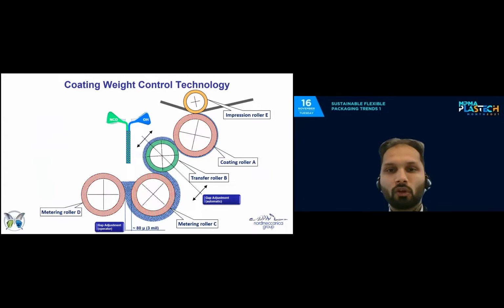And how does the Nordmeccanica 5-roller system work? Here we have 2 metering rollers, transfer roller B, a solid type coating roller, and the impression roller. The solventless adhesive, made of 2 components, the resin and the hardener, is delivered between the 2 metering rollers, and here there is the first calibration. From this calibration, we have the second calibration between the metering roller and the transfer roller B, and finally we have the third calibration, the fine tuning of the coating weight, between the transfer roller B and the coating roller. The beauty of this system is that the coating weight is a function of the rotating speed. And the Nordmeccanica patented system delivers the highest accuracy available on the market.